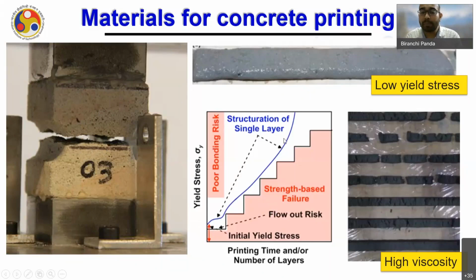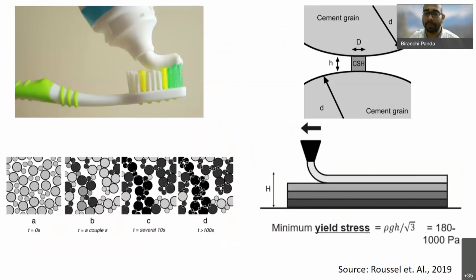So now again, we are coming back to the same concept like FDM, where the material has to be hardened with time, because now I want to deposit more layers. More layers means I want a structure which is beyond 2 or 3 meter height, so I have to deposit more layers. And in this regard, the material yield stress has to change with time, increasing with time, so that it won't collapse during the printing. So this is the key mechanism of designing material for concrete printing application.